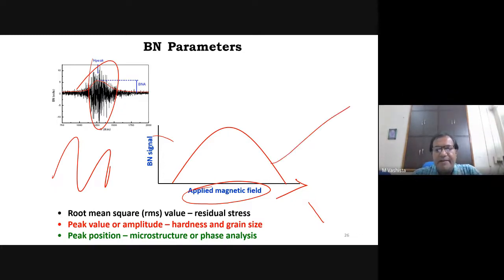The envelope has various parameters like its root mean square value, or peak position. First, I am considering the RMS value. The RMS value is a magnetic property because it is a magnetic signal. This RMS property is directly related to the residual stress. The peak value means this point. The peak value or amplitude indicates the hardness and grain size. And similarly, the peak position will indicate the microstructure.